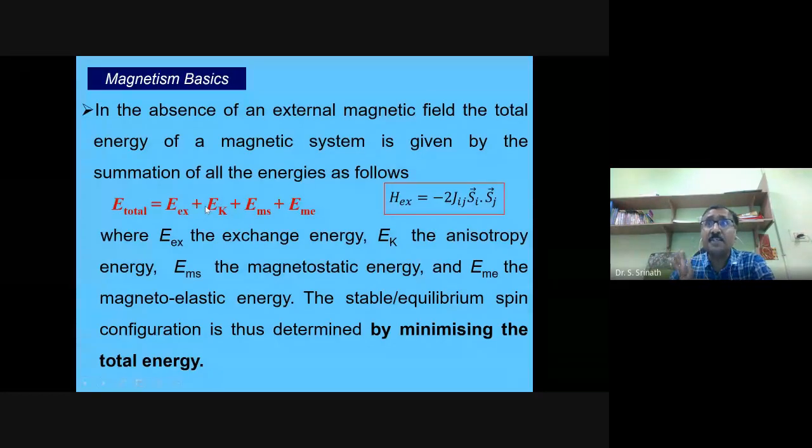the spins can point parallel to each other, so that the energy can be minimum. In fact, it so happens that in iron, the spins do point in all these 6 directions. So that is why you have domains. But then the question is, why domains? Why not a single domain? Why not they just be parallel to the x-axis?